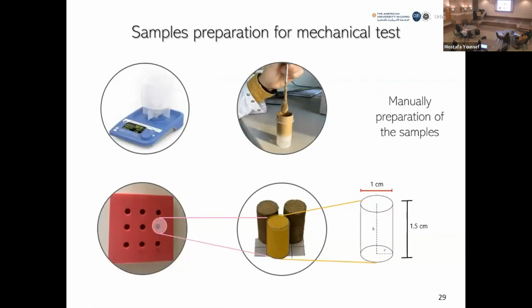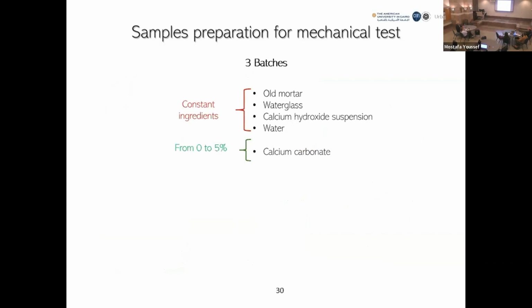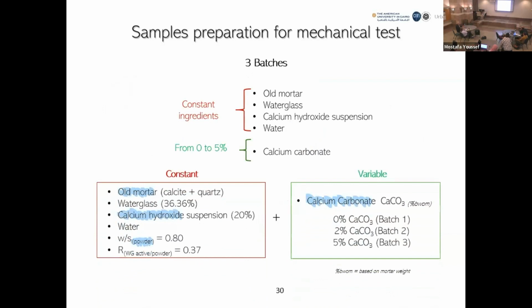All the samples were prepared manually, because as you can see here, I work on a very small scale. So I just mixed the mortar and calcium hydroxide with a small tube. Here I reported the recipes for all of the 3 batches that I used. In the red part, you can see the constant ingredients that I used for the 3 batches, and in the green part, the calcium carbonate that I added as an extra phase in 2 of the 3 batches. Here I reported in detail all the quantities, the concentration, the ratio of water glass, and the quantity of calcium carbonate, from 0% up to 5% in weight.